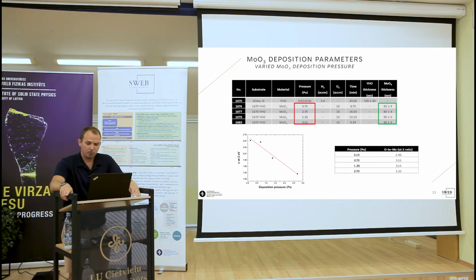We believe that density plays a more important role in photochromic properties in the end, because we see that the molybdenum trioxide itself is quite stoichiometric, even over stoichiometric, and you will see further in my lecture that our single layer molybdenum trioxide films aren't photochromic. That I already said when I introduced molybdenum trioxide, that stoichiometric molybdenum trioxide usually doesn't exhibit photochromic properties.